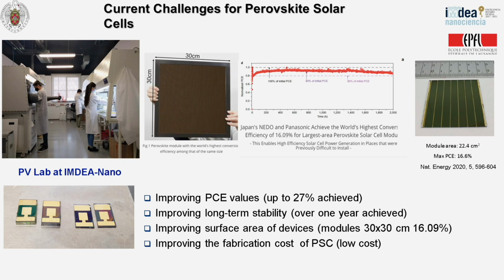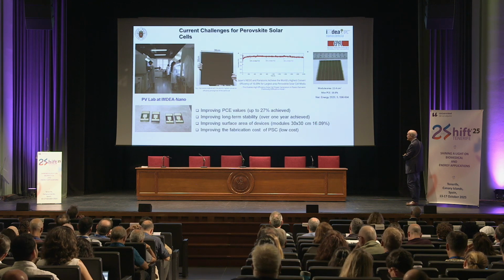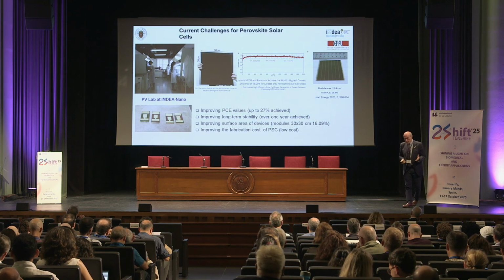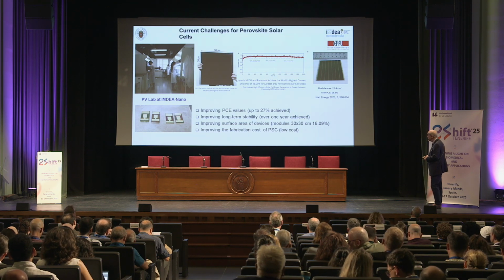It should be important to improve the efficiency, but 27% has already been achieved. This is more than enough for practical purposes. Also improving the long-term stability: it has now been proven that the devices can survive 1 year. Improving the surface area of the devices, the mini modules, here you can see some of them with efficiency around 16%, 30 by 30 centimeters.